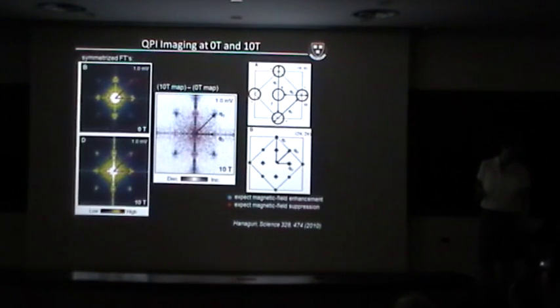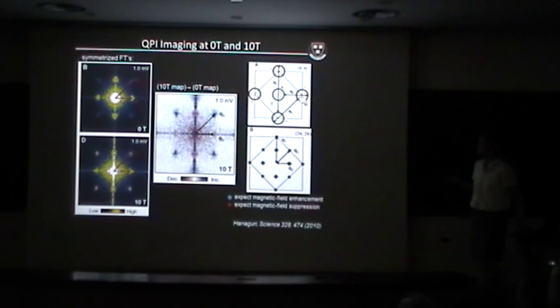Oh yeah, Q3 is expected to be enhanced, right? The blue ones are enhanced. So this is behaving exactly like we expect. So again, according to the vortices and magnetic scatterers, and sure enough, Q3 is enhanced as expected, and Q2 is suppressed as expected because Q2 is a sign-changing scatterer.